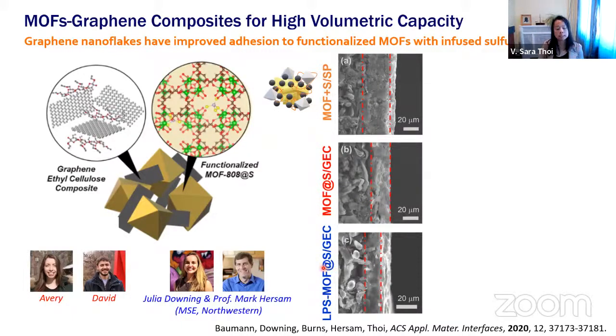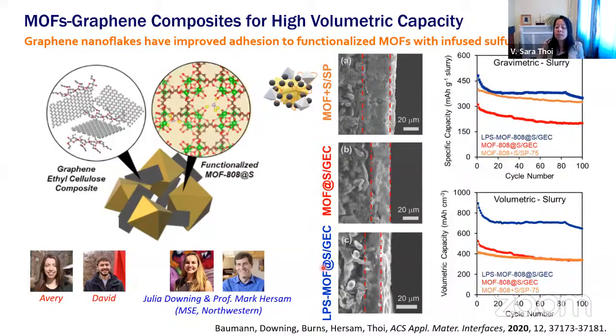Whereas if we took our MOF infiltrated sulfur with our graphene, we get relatively thin electrodes both for the unfunctionalized and the functionalized MOFs. What the effect of this is that gravimetrically, we see that our thiophosphate MOFs, shown here in blue, perform well. Now, I will note that we are dividing by the gram of slurry material, not the gram of active material. And you'll see that our functionalized material does work really well, but it's not significantly higher than our 2 other materials shown here. However, volumetrically, you see that our capacity actually does shine. We actually get much higher volumetric capacities than our other 2 MOF materials. And that really tells us that this new strategy of making new battery composites is important for commercializing this kind of technology.